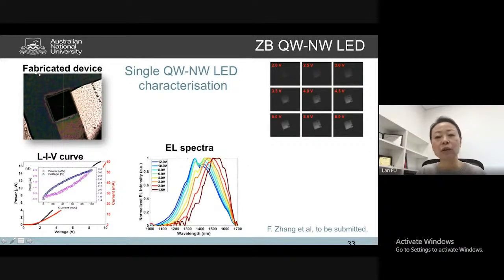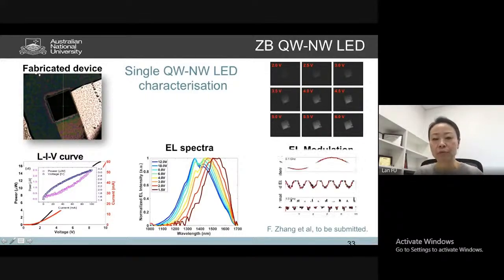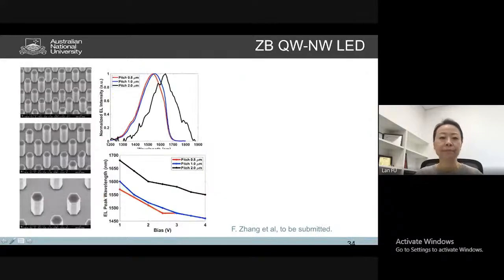And this is the electroluminescence, again showing that we have a very nice broad electroluminescence up to 1.6 micron, and the wavelengths can be tuned by tuning the voltage from 1.5 volts to 12 volts. And this can also be modulated quite fast at the gigahertz level, which is very useful for optical communication applications.